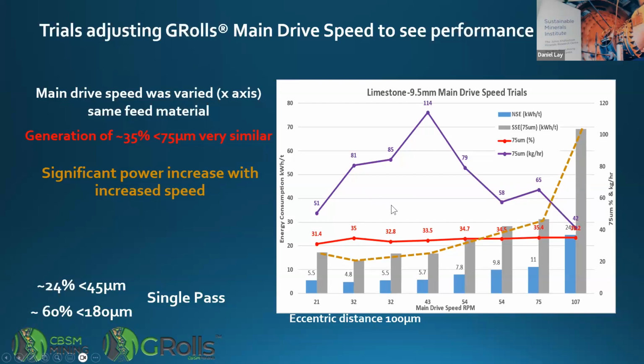We think that's because with increased speed, you're going from crushing and shearing to straight crushing and trying to jam the material down through that gap, and so you're exerting lots of energy. But again, as you slow it down, you're actually starting to increase your energy requirements. So there's probably a sweet spot here for a certain drive for that material.